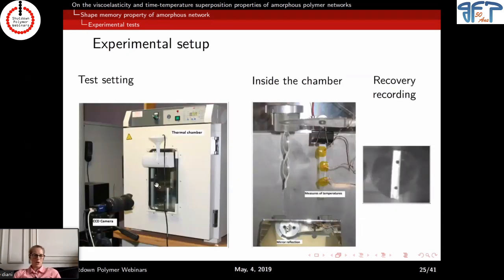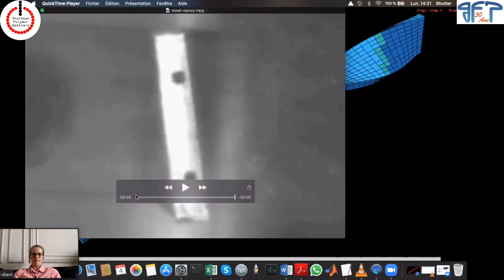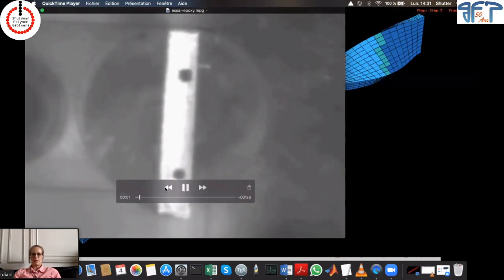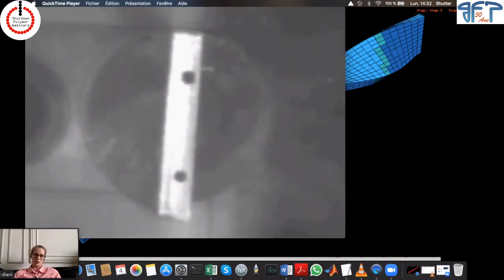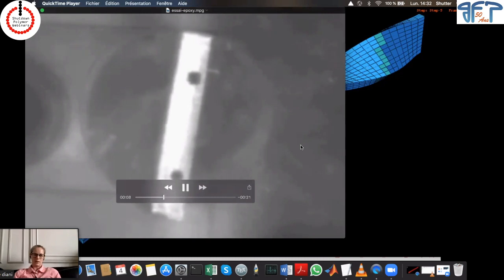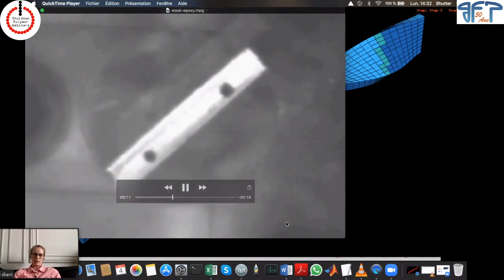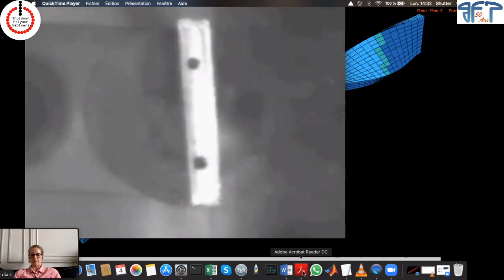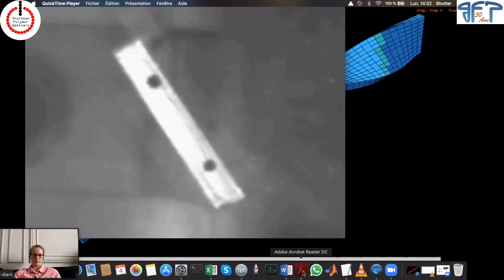For that, we had a setup with a thermal chamber and a camera in front. You see the deformed sample and a mirror reflection, and we painted 2 dots, allowing us to look at the recovery of the sample in terms of angle of recovery with the temperature, while we were measuring the temperature change over time.